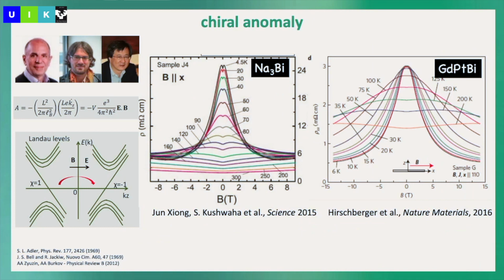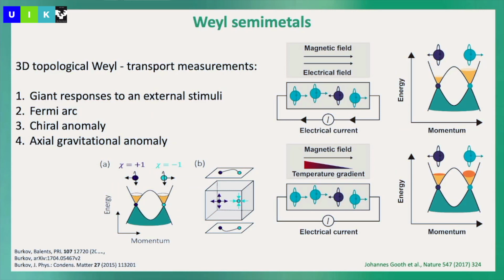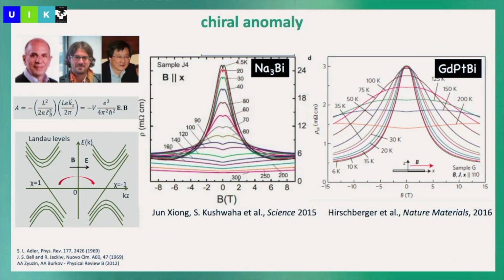Okay, so this is this chiral anomaly term, and the idea here was that if you have the electric field and the magnetic field here in parallel, the prediction was a negative magnetoresistance effect. And this is always the problem with the quasi-chiral anomaly, you know. There are many other reasons eventually to see a negative magnetoresistance effect. But anyway, this was the prediction, and the first measurements were done on these